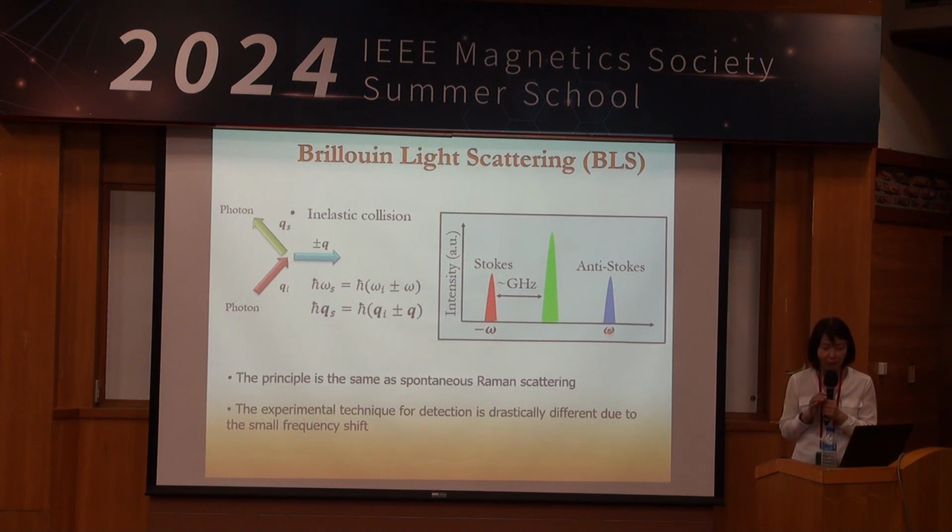Most people don't understand this: a Raman measurement is actually a single-particle measurement, meaning the vast majority of the time, you don't get either a Stokes or anti-Stokes photon. You're actually waiting a long time for that scattered photon to arrive. When you measure a single scattered photon, you have created one quantum of magnon, or annihilated one quantum of magnon, in the material. So that very mundane process is already a single-particle process. It's a quantum process, okay?